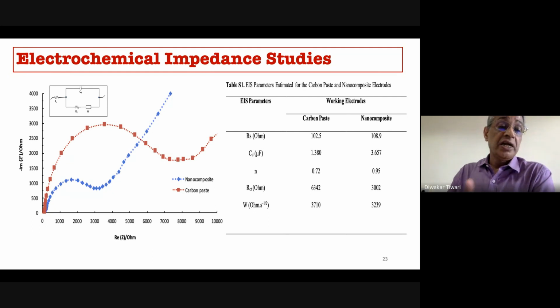So this is the Nyquist plot on the left-hand side, and this is the semicircle of the Nyquist, and with that we have optimized the RCT value. When the carbon paste electrode was there, the RCT was 6,342 ohms, but that has decreased to 3,000, almost half of the value. The semicircle also, you can see, is significantly decreased. So what we can say is that the charge transfer reactions at the electrode surface can take place easily, and better sensitivity one can get.